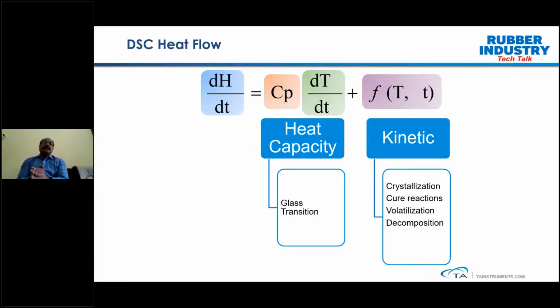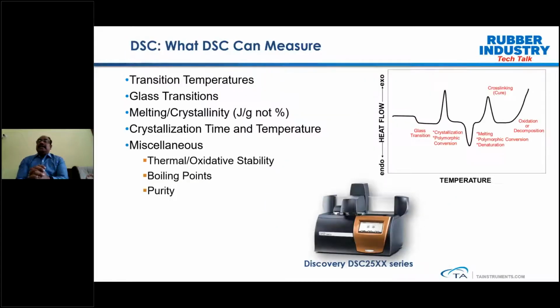So that the DSC can detect a heat flow change when, for example, a sample undergoes some changes with respect to kinetics. Let's say you have a rubber compound which undergoes some curing process; that can be measured by kinetics as a function of temperature. That also is going to alter the heat flow. So this will give the complete information on how the sample is going to change its transition or the associated kinetic transition, and we are able to quantify the heat associated with that particular transition. So that's about the Discovery DSC25XX series.